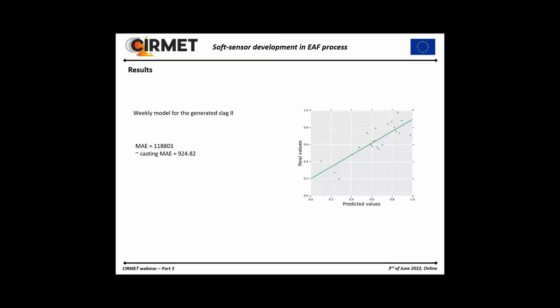We used a random forest method in this case with the leave-one-out cross-validation, and you can see there the obtained error, taking into account that that's a weekly estimation, so the quantities are quite big. But we also estimate the MAE per casting, taking into account the average number of castings per week. So this we did with a measured quantity of the slag, because remember that at the end of the week the furnace is cleared out, so this value is reliable.